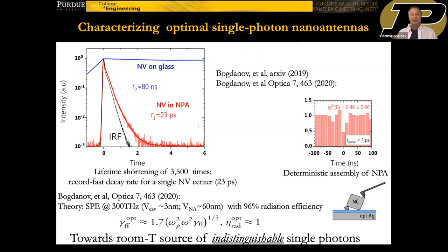Whereas with an antenna size of, let's say, 60 nanometers that efficiently outcouples, we showed that the radiation efficiency could be as high as 96%, and photons are emitted at a rate of 300 terahertz. That happens because this efficient antenna outcouples photons before plasmons decay. And potentially, with this rate, 300 terahertz, the typical decoherence time is 1 picosecond, or let's say a few terahertz.